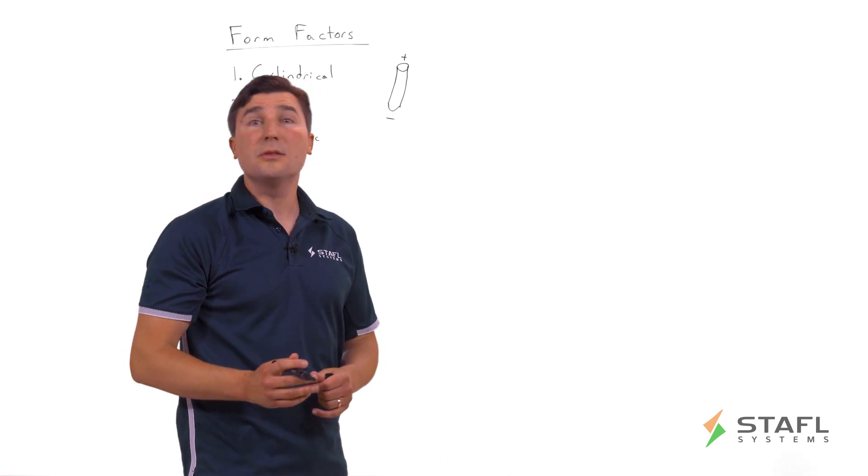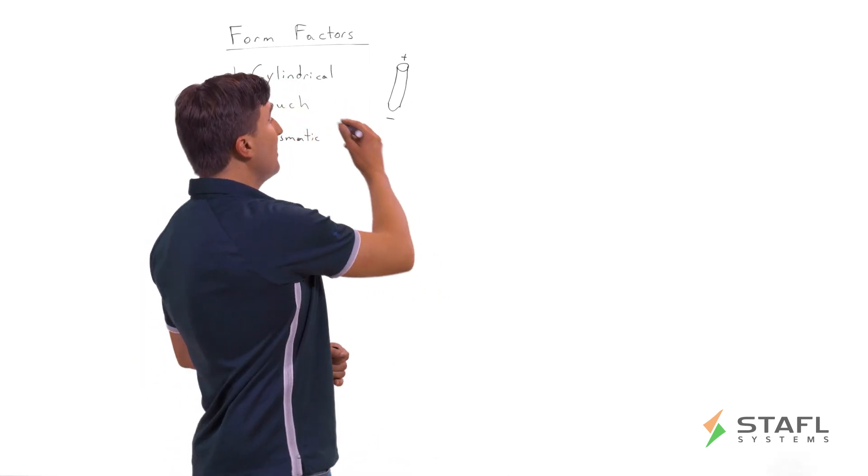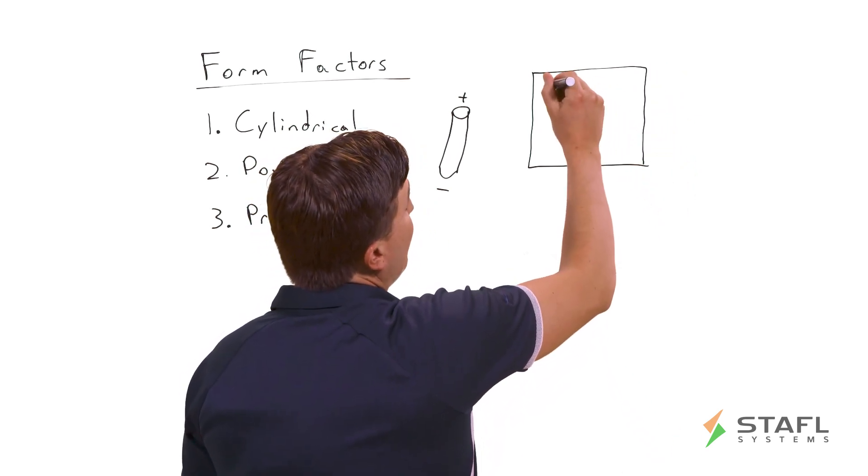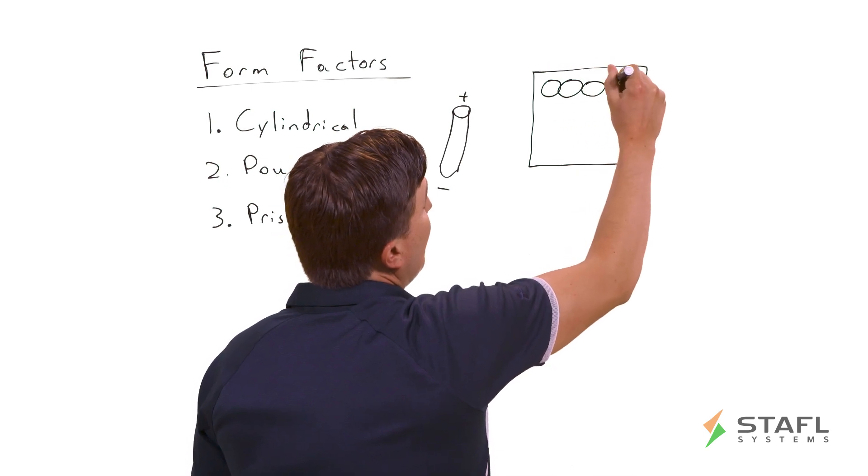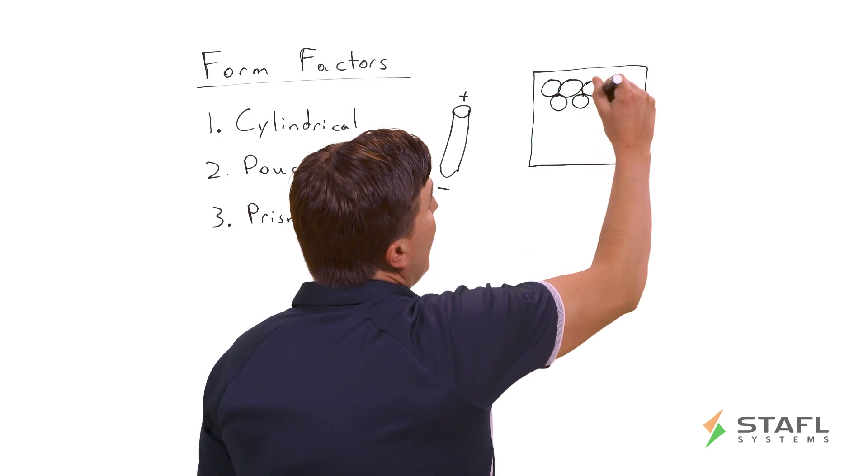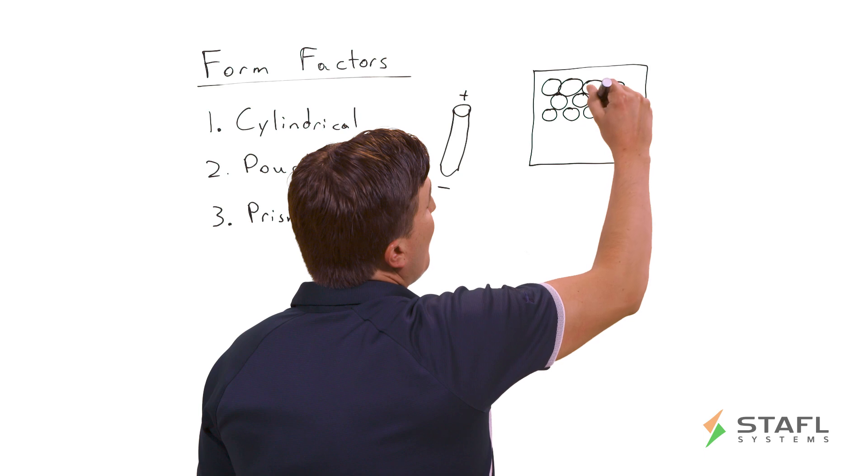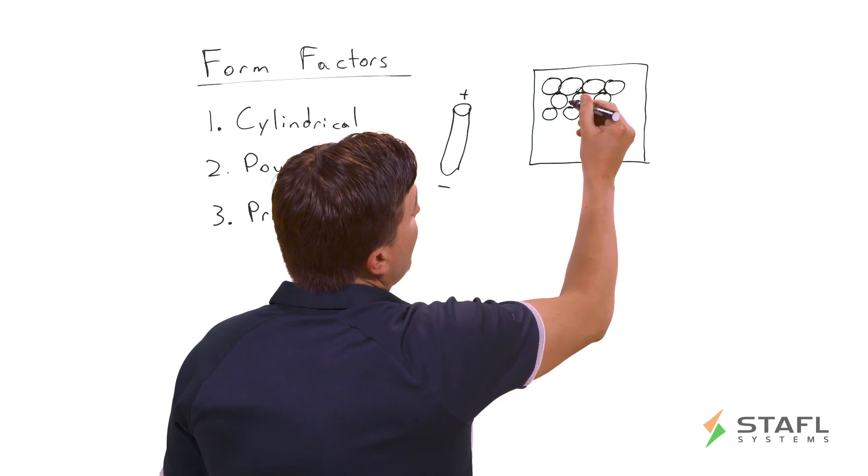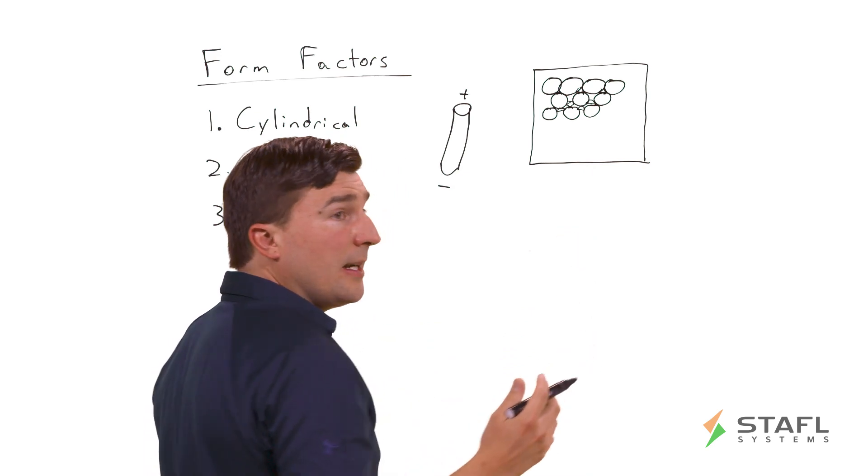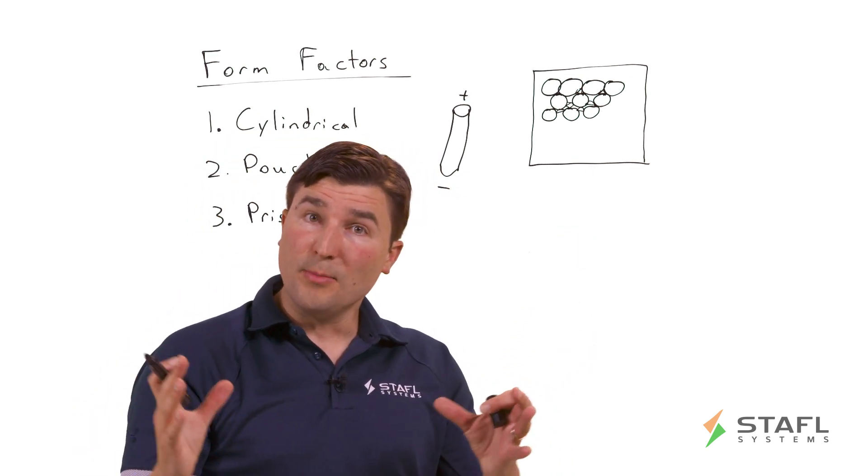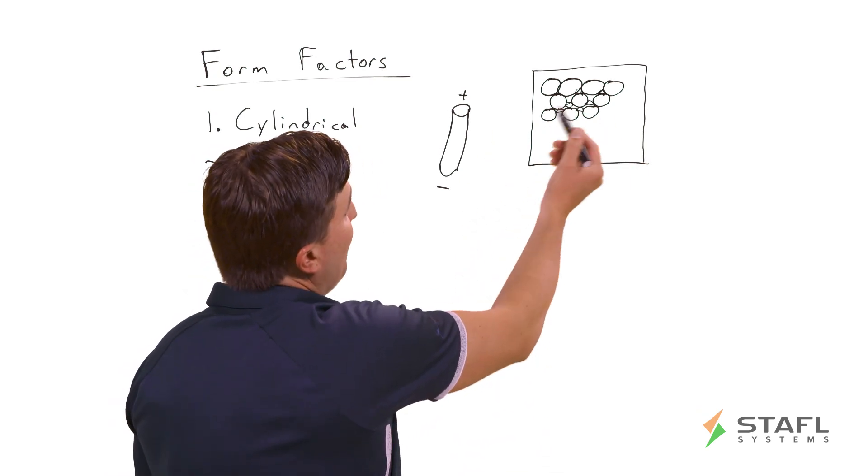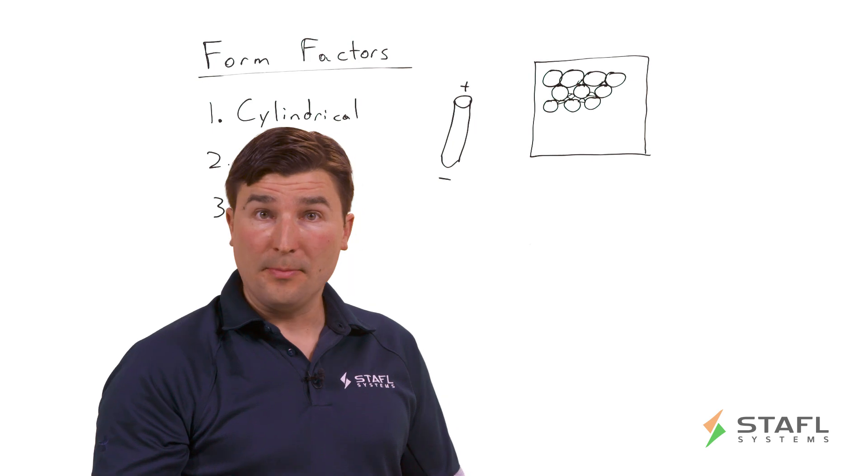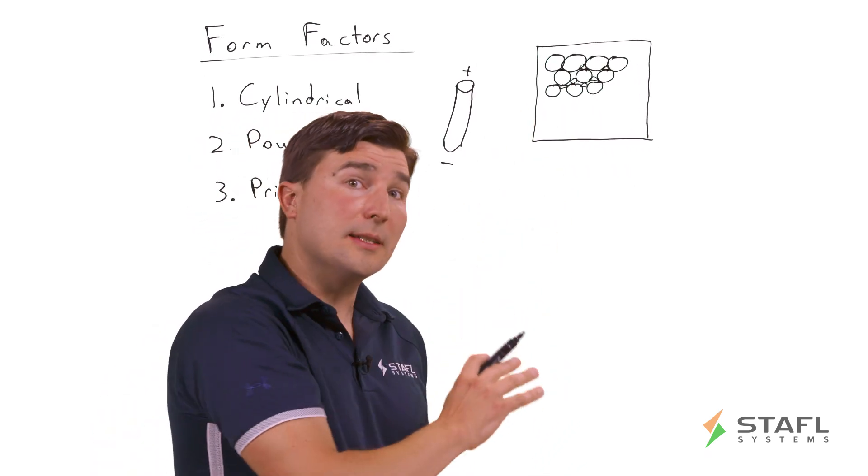There are some drawbacks, however, to the cylindrical cell. For example, because of the fact that there are circles, packing them in a pack is actually quite difficult. Let me show you. So, for example, this is a top view and if I had to pack a number of these cylindrical cells together, you'll notice even if I use the hexagonal packing architecture, where it's kind of a honeycomb pattern, there are voids in between the cells necessary just due to the circular form factor of the cell. So that can make it difficult to get the same amount of energy density in a small volumetric space. Also, because of the shape and circular nature of this, removing heat and thermal rejection from these cells is a little bit more difficult. It's certainly possible, but it's a factor to consider that's more difficult with these cells than the other form factors.